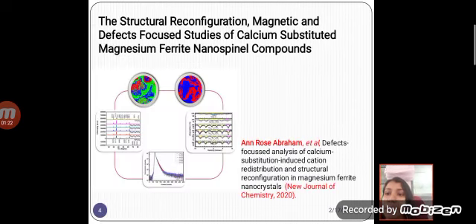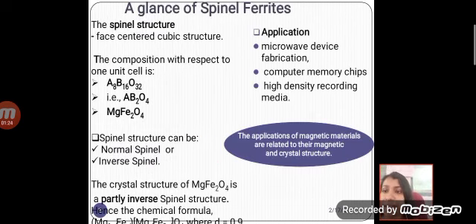So let us see a glance of spinel ferrites. What are spinel ferrites? The spinel structure is actually a face-centered cubic structure. The composition with respect to one unit cell is A8 B16 O32, which can be simplified as AB2O4. So in our case, this becomes MgFe2O4, where magnesium occupies the A sites, iron occupies the B sites, and oxygen occupies the remaining sites.